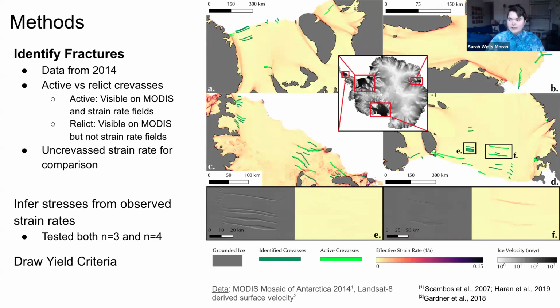So to go briefly over the methods, the first step was to identify fractures. Then from the fractures, we inferred stresses from observed strain rates, and then we drew yield criteria around the inferred stresses to try and delineate between stresses present in crevassed versus uncrevassed ice. For identifying fractures, one of the main challenges is that a lot of fractures visible on optical imagery are inactive crevasses. So to filter for this, we filtered out inactive crevasses by looking for crevasses that were visible on both optical and strain rate fields.